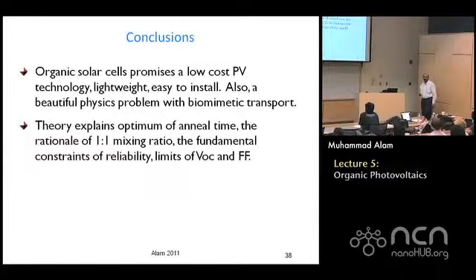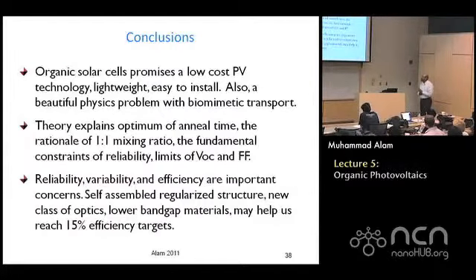Now, I explained to you very simply how percolation plays a role, how the reliability and the solubility, the same physics that governs phase segregation, makes it easy to work with, is the same one that makes it less reliable. So reliability and performance are flip sides of the same coin, and should be considered as such. And this variability I told you about, when you have series connectedness, is a fundamental aspect of our solar cells. Because of the series connectedness, you cannot have cells that have huge variability. Because if you have that, you lose several percent of your efficiency by the time you connect them all up together, and that's not really very good.